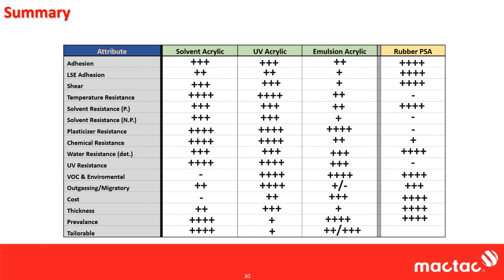Emulsion acrylics, between a 2 and a 3 here. It's very easy to mix something into an emulsion acrylic, but actually there's not a lot of options for what you can mix into an emulsion acrylic. In a lot of cases, we find it easier to find raw materials compatible with UVs more so than emulsions. And finally, for rubber, rubbers are very easily modified and tuned. In fact, in terms of all the adhesives, you can create just an infinite number of rubber-based PSAs. If you're talking solvent rubber, it's very easy to modify them. But if you're talking a hot melt rubber, it's difficult because of the same thing with UV acrylic. You've got to melt it. You've got to add the special mixers. So that gets between a 1+ and a 4+.